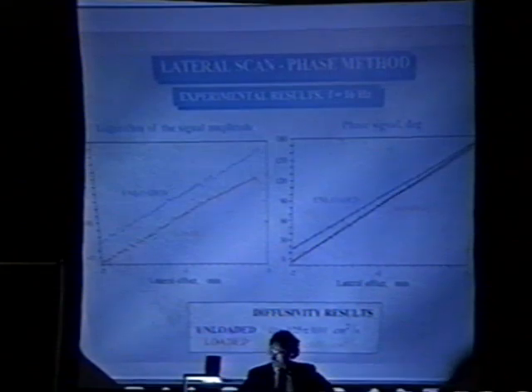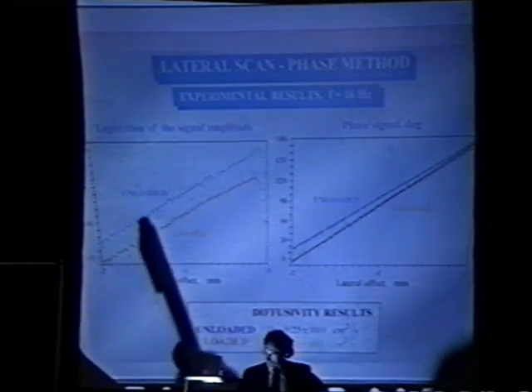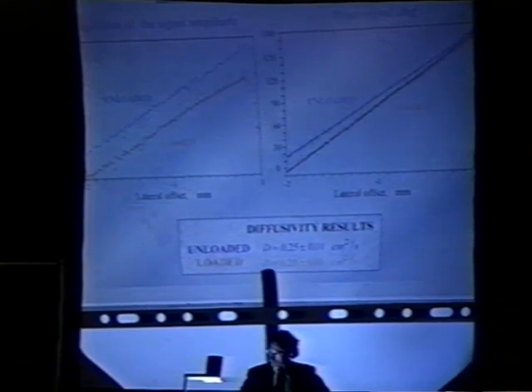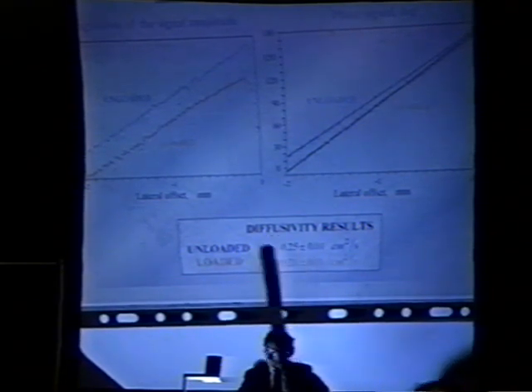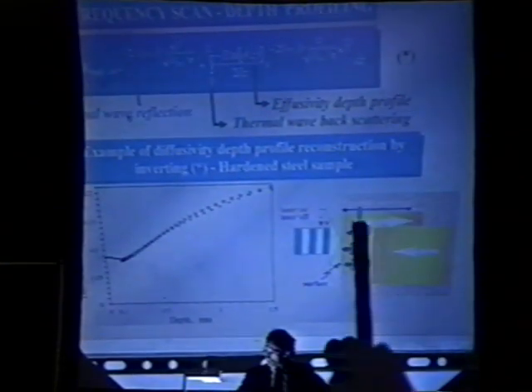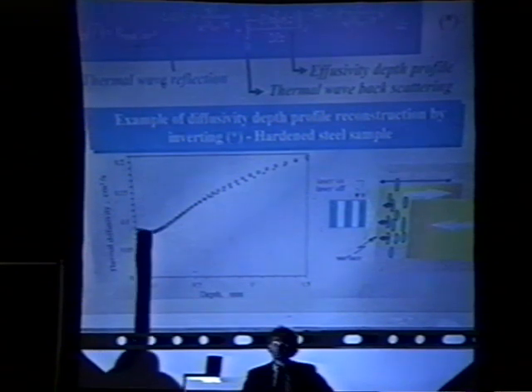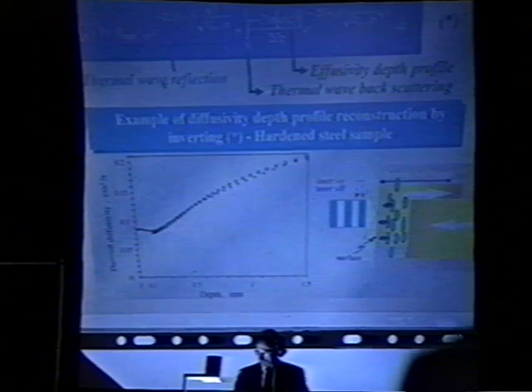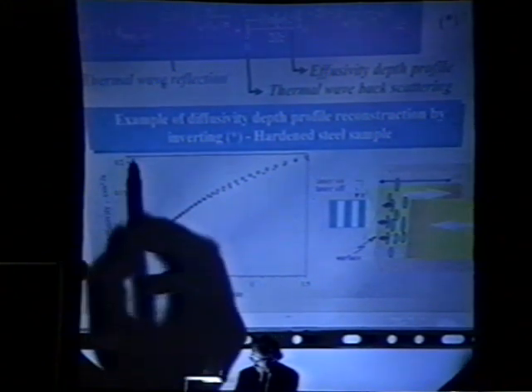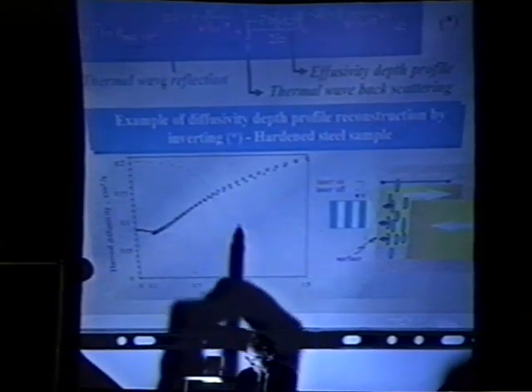By applying the technique to loaded and unloaded samples, we obtained such values for thermal diffusivity. So the thermal diffusivity decreases by about 20% in loaded material. And this is a very important point because we know that the material changes properties from a metal to a hydride. With a somewhat more complicated mathematical approach, we can study this effect for a non-homogeneous media, obtaining such a profile of the thermal diffusivity inside. And this profile is obviously correlated with the concentration profile. For more details, see the poster.